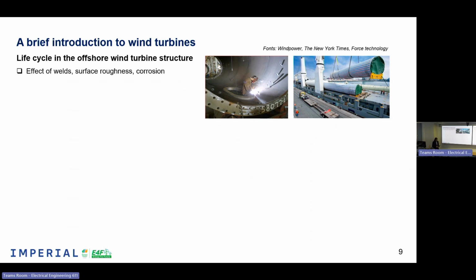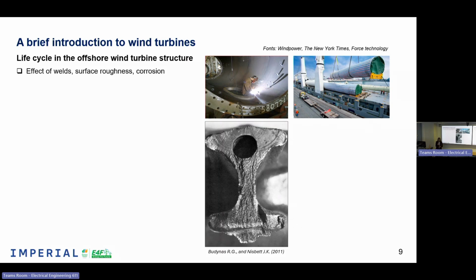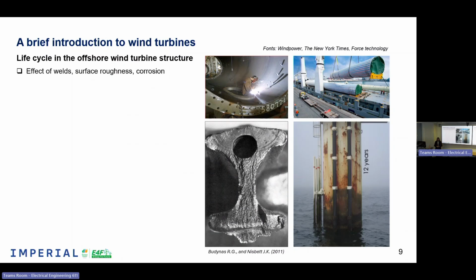We have surface roughness, which is very well known to be critical for fatigue because the different waves act as stress concentrators, as we will see later. And then we also have corrosion, a chemical reaction between the sea and the metal, or the wind and the metal, that generates pits, and the pits evolve until cracks propagate. Moreover, these two are completely related, because we want to put some painting on to avoid the corrosion, but to put the painting on, we need to generate surface roughness. So we have to decide which one is less bad, let's say.